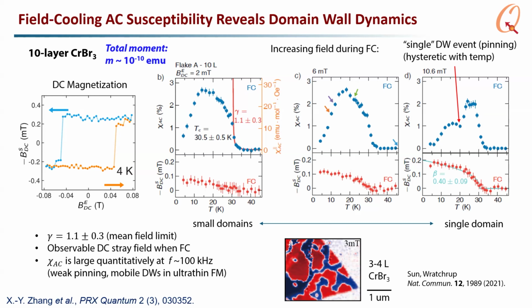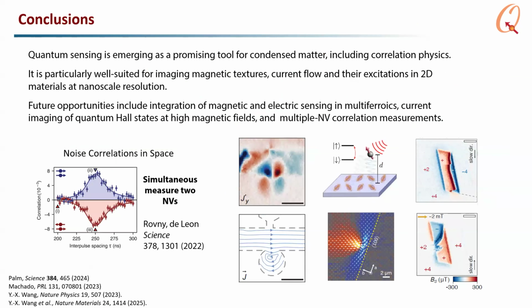This is a very different regime than your SQUID MPMS, where you assume your sample to be a point source. Here, the detector is a point source, and the sample is effectively an infinite plane, right? So that's all to say that if you measure with different NV centers at different points, you might get something different for this sample. But that's not bad for a first attempt to measure the susceptibility directly. And for these very small samples, there are only a couple of techniques that can measure the AC susceptibility, AC MOKE and AC SQUID.